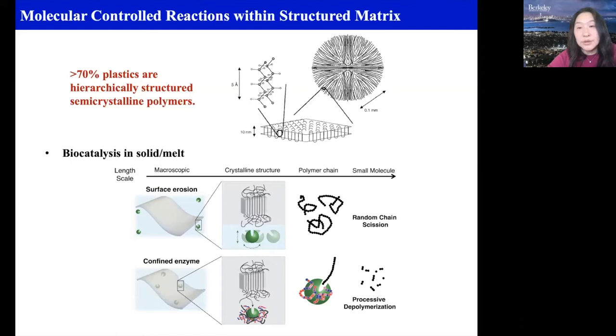So over 70% of plastics turn out to be semicrystalline polymers. That means that they form hierarchical structures across different length scales. At the molecular level, at the monomer level, they pack into a unit cell, typical unit cell with dimension of a few angstrom. And then the polymer chain acts as a stem. The stem folds back and forth and they form lamellae. And the lamellae are essentially highly anisotropic thin sheets, typically 10 to 50 nanometers in thickness, and they can grow in the range of microns, so tens of microns in plane.